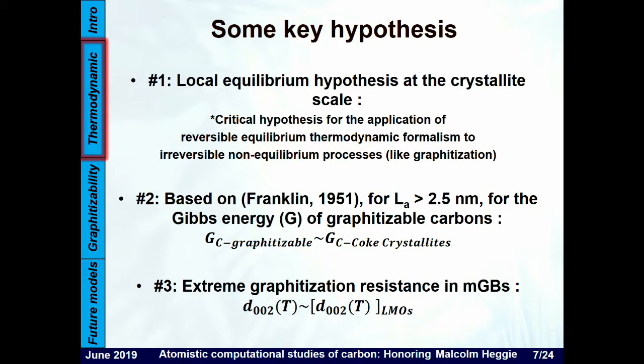So the key hypotheses of the work are as follows. First of all, we suppose local equilibrium hypothesis at the local scale for crystallites. As I said in my structure, you have LMOs, which are very big entities, and you have very small crystallites. What's very important for the model to work is that you can consider that at the scale of a crystallite, the system is in equilibrium, even if at the scale of the LMO and even bigger, the system is not at equilibrium.